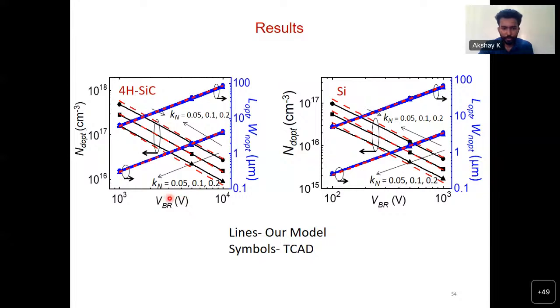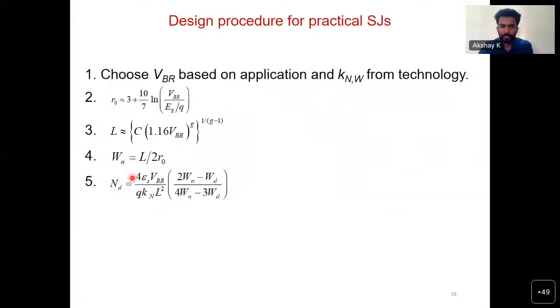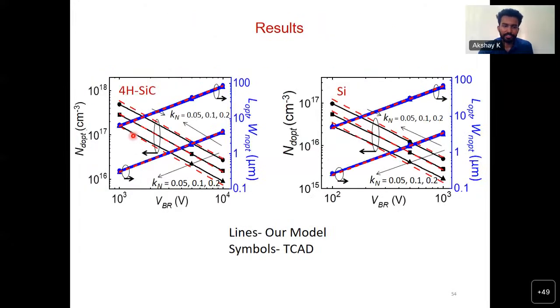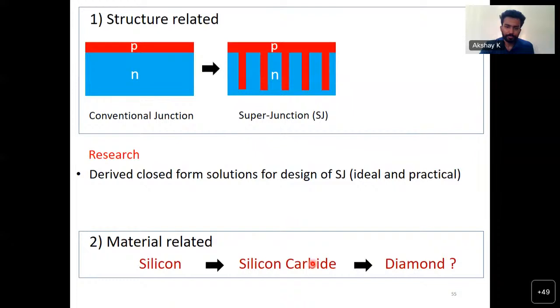This is the model. Suppose you want to make a 2 kV device out of silicon carbide, a 2 kV superjunction from silicon carbide. So here is the 2 kV. You see what is the doping and the pillar length and width from this chart or from this model. This is nothing but the plot of these equations. You can use the equations in principle, but this is just a plot where we did all the calculations and summarized the whole result. That's all. And it is matching very well with TCAD estimations also. So that was the first thing that we did.